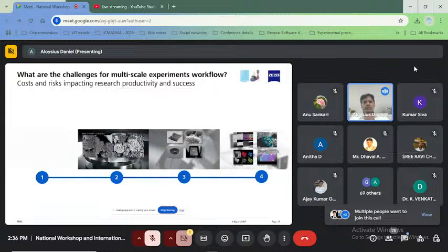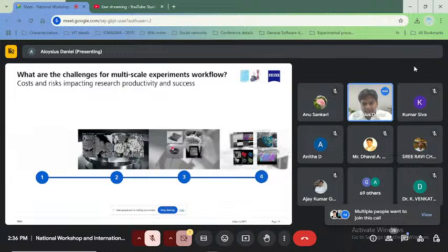So that's what we do, starting with identifying using the X-ray microscope, and then accessing the area or the region of interest that has been identified, and then we prepare the samples. It could be a lamella preparation for TEM analysis, or thin probes for atom probe tomography, or we can also start preparing samples for micro pillars for tensile testing using indenters, or it could be prepared for EBSD or crystallographic data collection using the electron backscatter diffraction patterning as well, or it could be simple chemical composition as well.